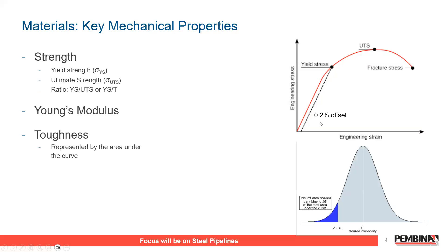Toughness is represented by the area under the curve. How does this relate to pipeline steels? The ratio of yield strength to ultimate tensile strength has changed over time. The closer it is to one — meaning these two points happen more concurrently — that means there's less time at the same strain rate to respond to the source causing the strain. Modern pipeline steels have changed the shape of the engineering stress-strain curve such that the Y/T ratio has become much larger, meaning reduced strain capacity after yield — also referred to as low strain hardening.